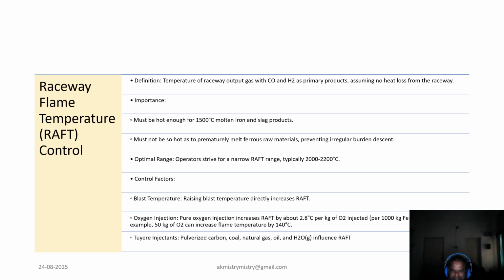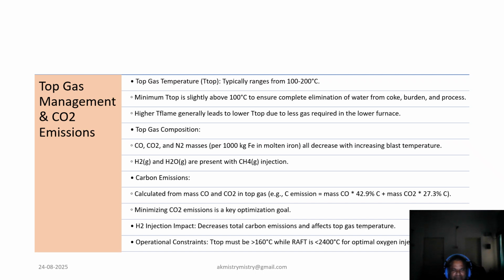While tuyeres are usually installed horizontally, modeling tests have indicated that raising them a few degrees could shrink the raceways. Now coming to our next slide, which is very important and is about effective top gas management. As we all know, effective top gas management is extremely crucial, especially concerning CO2 emission and carbon capture. So beyond standard top gas temperature, which typically ranges from 100 to 200 degrees centigrade, the industry is heavily invested in carbon capture storage technologies.